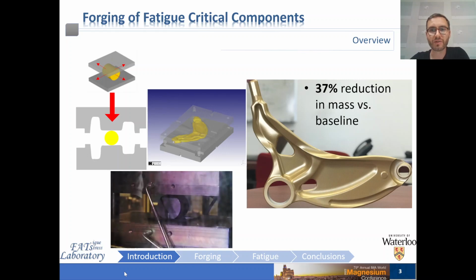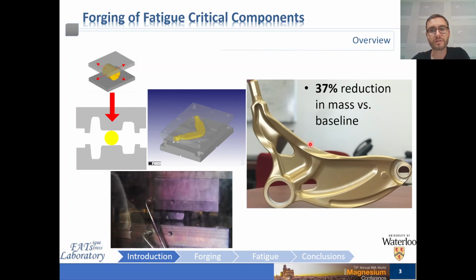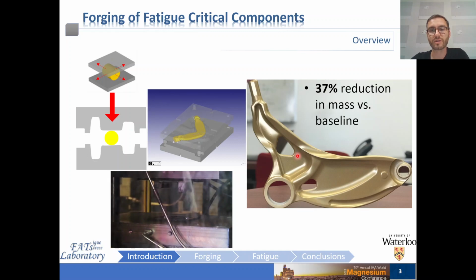As somewhat of a prelude to my talk, I'd like to present this photo of the final production component, and it's a production viable component which we produced as part of this work. Not only because this may be visually appealing to some of the audience, it did win a few awards already, but really to emphasize the main objective of this work, which was vehicle lightweighting. We targeted a fatigue critical automotive suspension component, and we were able to achieve a 37% reduction in mass versus the aluminum baseline. This type of paradigm shifting improvement is not new to any of you in the magnesium field.